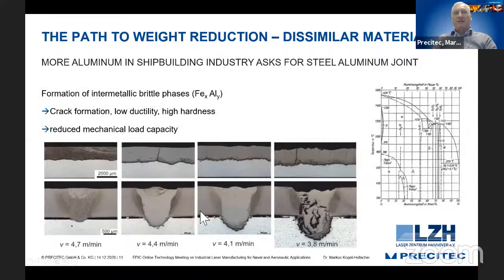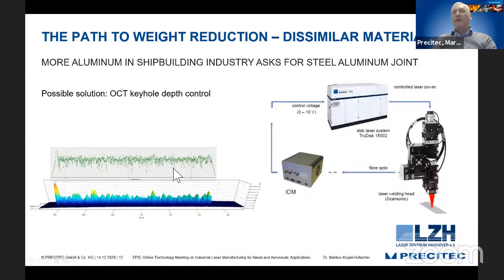You see here that if you do not weld deep enough, you don't get a joint between steel and aluminum. And if you go too deep, you will get brittle intermetallic phases. So that's why it is crucial to have a sensor which is able to detect the penetration depths. And for that, we implemented our well-known OCT device to measure and to control the penetration depth. That was combined with a Scansonic processing head in that project. And now we were able to directly control the penetration depths.